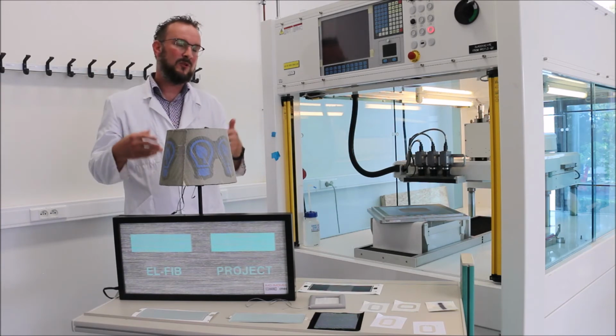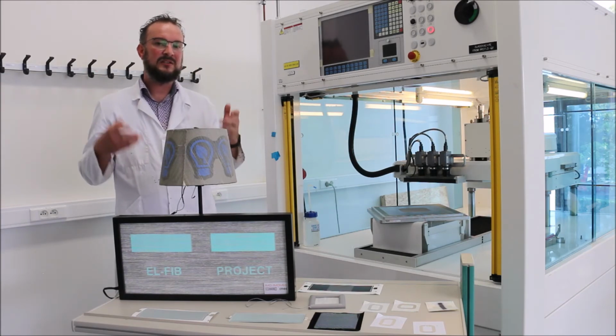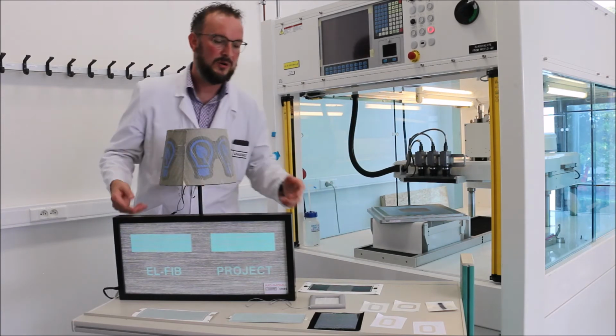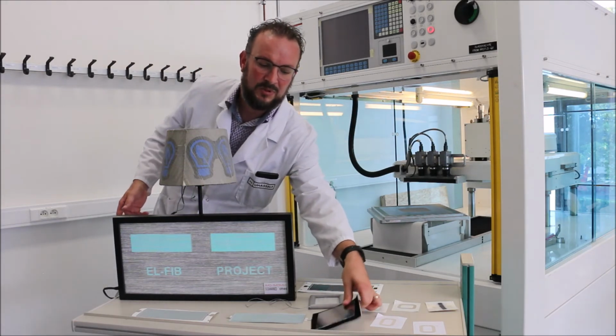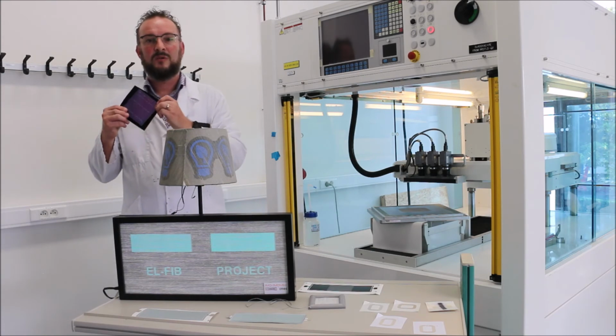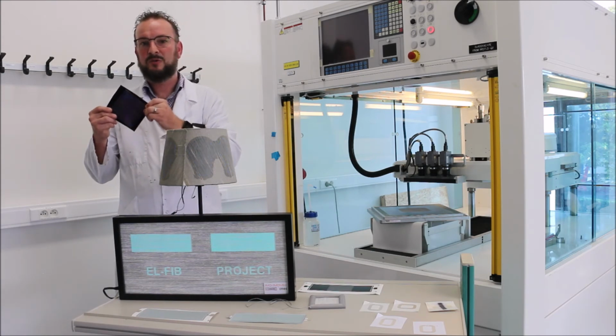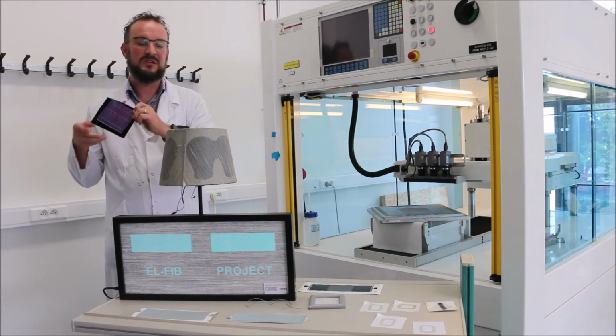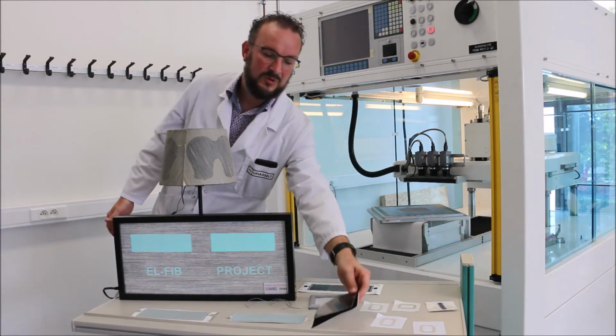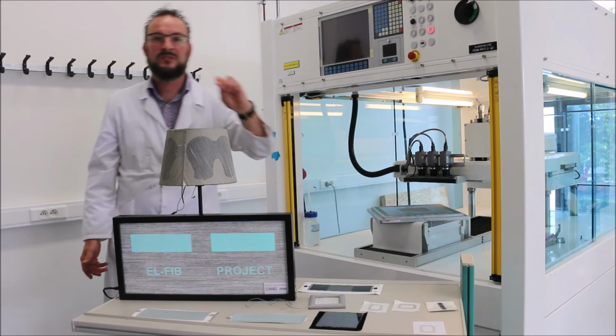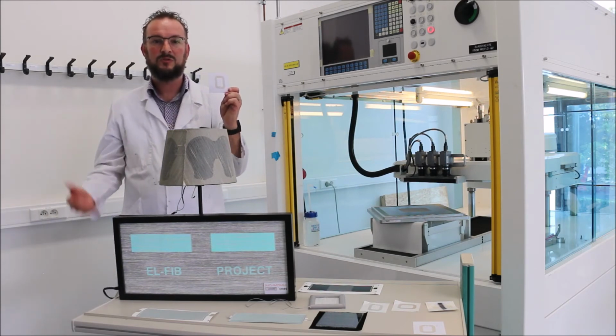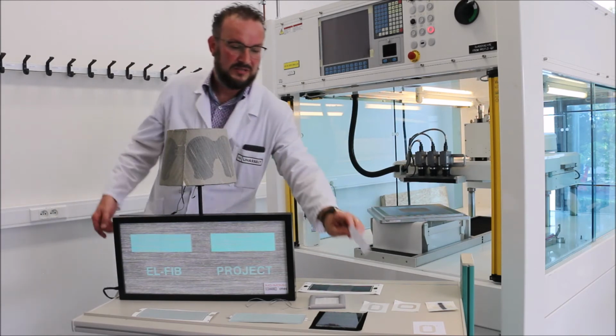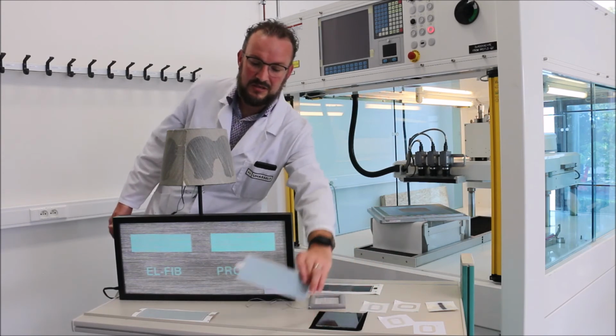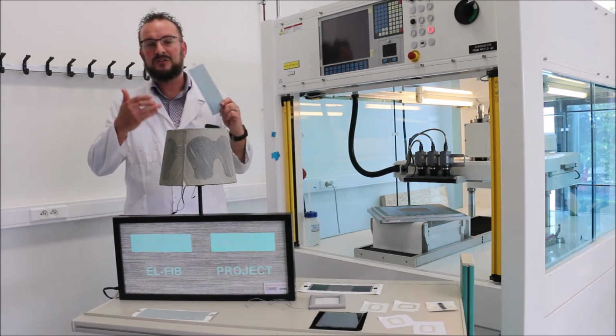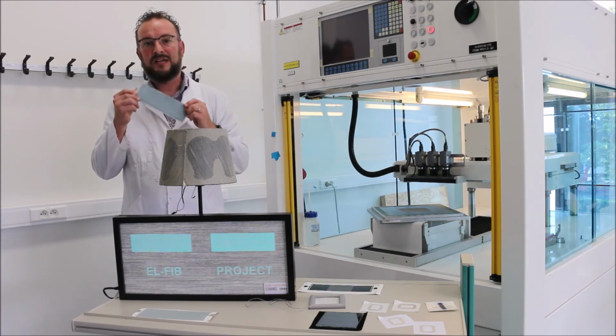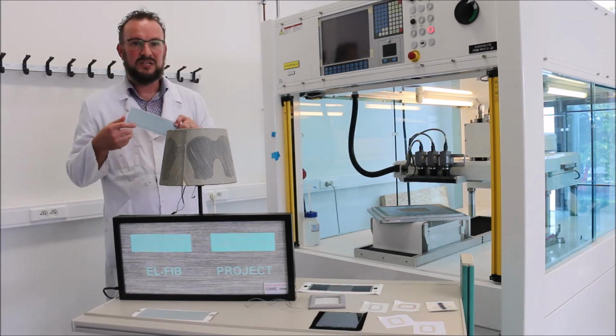And in comparison to, for example, inkjet printing, the line width is comparable and can go down to around 50 micrometers. An example of this you can see here, where we print metallic tracks used for interconnections in PV applications. Other applications that we do with screen printing are, for example, this antenna that can be used for smart packaging, or these light emitting devices that you can see here, where we print several layers on top of each other, and by applying an AC voltage to it, they will emit light.